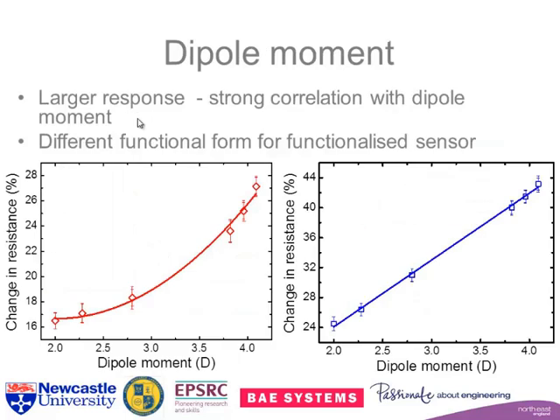We looked at dipole moment. Well, our original works, this is on the non-functionalized material. Water has a dipole moment of about 1.8, and because we don't control the humidity in the lab very well, we looked at dipole moments above those of water, and we see what we considered to be an exponential behavior. We could have a linear fit. It depends on how good a curve you want.